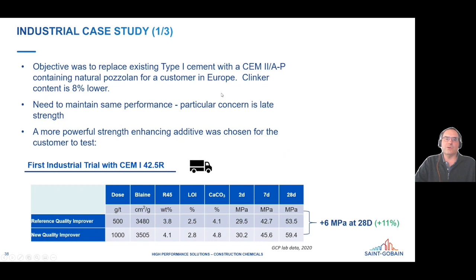So the approach that GCP would then have is we would do a lab screening just on their cement one to see which quality improver formulations that we have would be very effective on their cement. And so we found this one here on the second row that increased the 28-day strength of their cement one by about 6 megapascals. So that's a big increase, and that gives you some room to work with. So they didn't need to be higher than 53. So if you can increase it to 59, now you can dilute it with something else and bring it back down to 53. And that's what was done here.